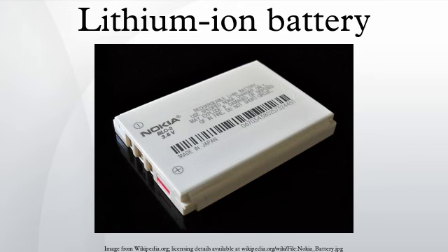The rate of degradation of lithium-ion batteries is strongly temperature dependent. They degrade much faster if stored or used at higher temperatures. The carbon-negative electrode of the cell also generates heat. High charge levels and elevated temperatures hasten capacity loss. Poor ventilation may increase temperatures, further shortening battery life. Loss rates vary by temperature: 6% loss at 0 degrees Celsius, 20% at 25 degrees Celsius, and 35% at 40 degrees Celsius.